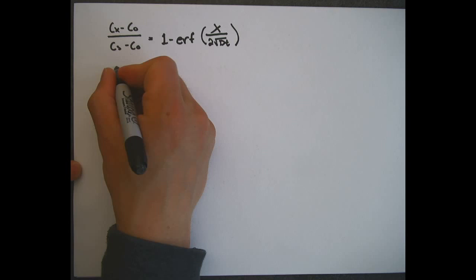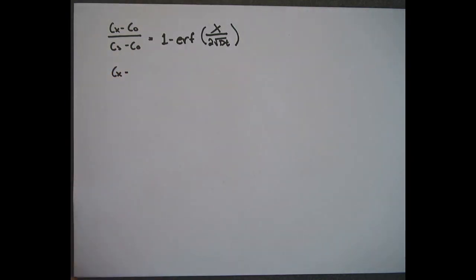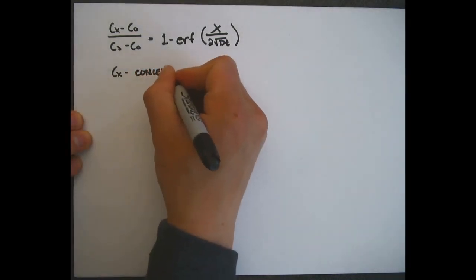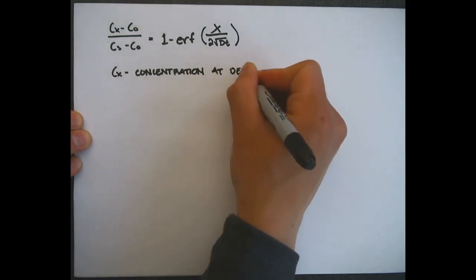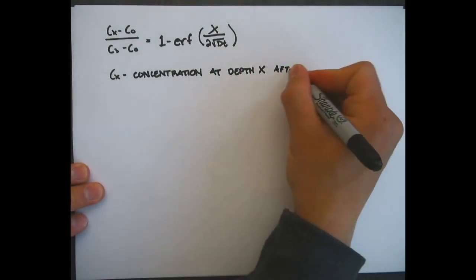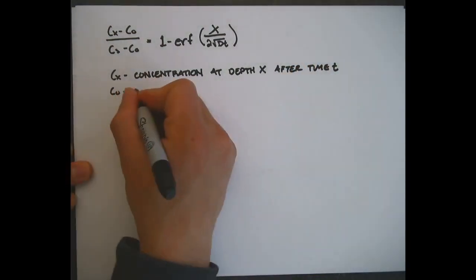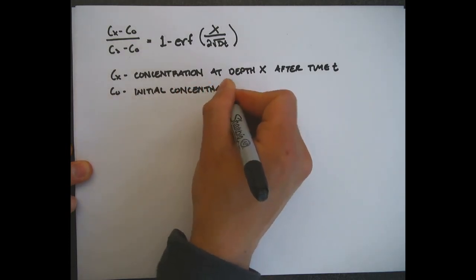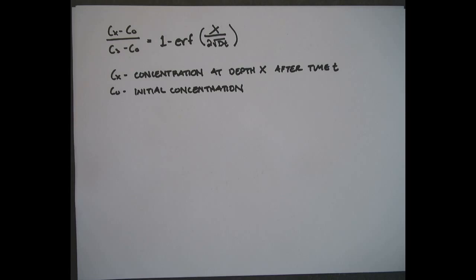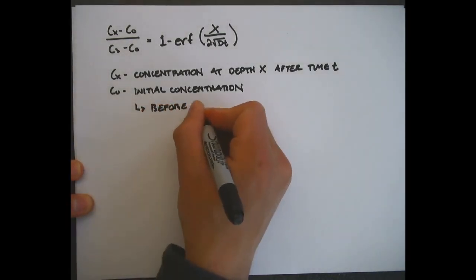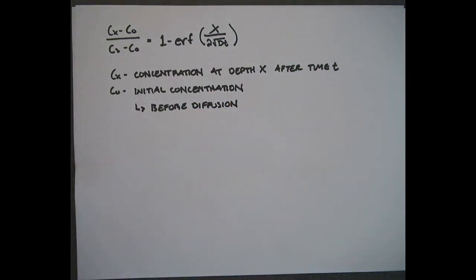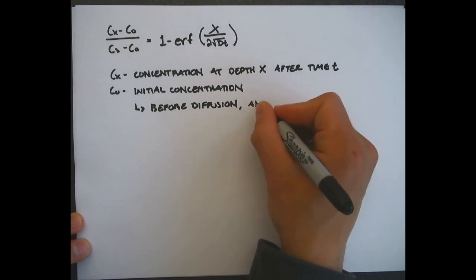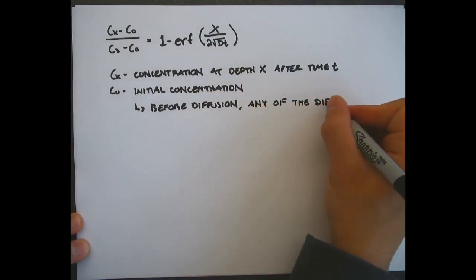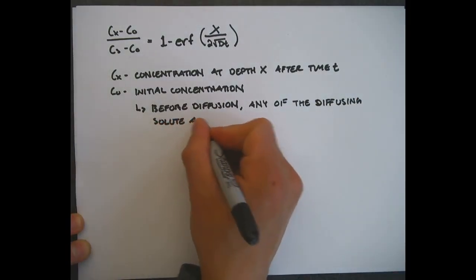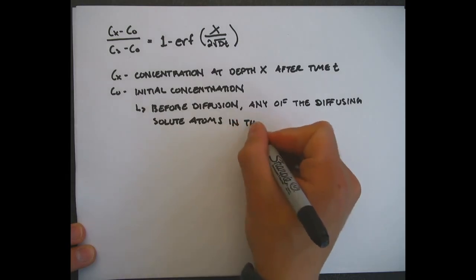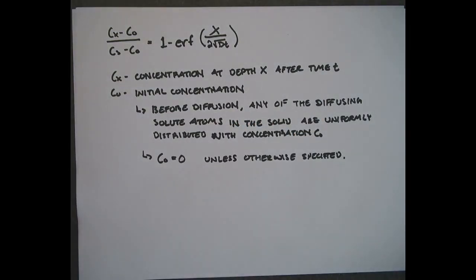Now, you may be wondering what these variables stand for. Well, C sub x is a concentration at a certain depth at a particular time, t. This makes sense because x stands for our depth or position, where C sub x is our concentration at that depth or position. Now, C sub o is the initial concentration of the solution. The boundary for that is that before any diffusion, any of the diffusing solute atoms in the solid are uniformly distributed with a concentration of C sub o. What we've seen normally in our equations and our assignments and problems that we've had to work through is that unless it is otherwise specified, our C sub o is normally 0. And that makes sense because our initial concentration, unless diffusion has already occurred, is going to be 0.